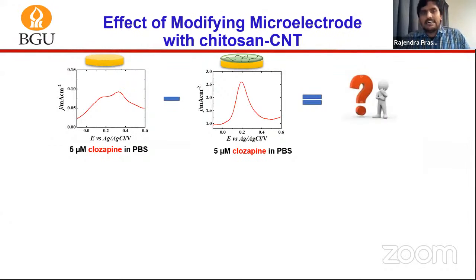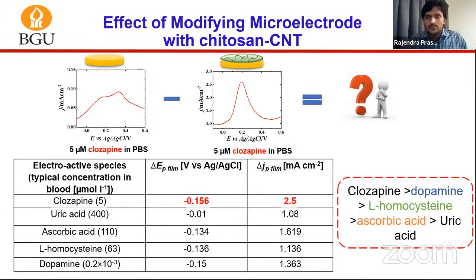We also tested the electrocatalytic activity and how modifying the microelectrode with chitosan-carbon nanotube is going to affect the electrochemical behavior. For that, we took 4-5 redox molecules that have a very close redox potential to clozapine, and we characterized the effect of modifying the microelectrode with carbon nanotube in terms of shift in the peak potential, and also in terms of the shift in the peak current density. Here you can see with clozapine there is the highest shift in the peak potential, and also a change in peak current density of around 2.5 times, meaning that the carbon nanotube modified microelectrode is highly selective for clozapine.